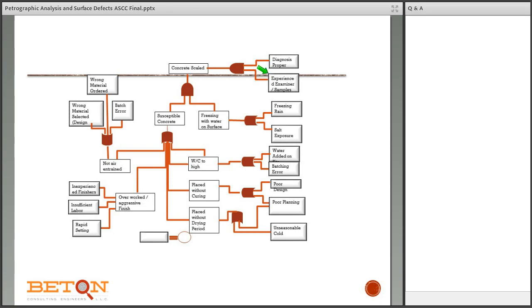If you have a sulfate attack, if you have a salt attack that occurs, or even soft water attack that would occur in a place where there's never freezing and thawing, you can draw the conclusion that you have scaling due to freezing and thawing if the diagnosis is not done properly or the examiner is not experienced. And it's very important for us not to end up in that position.